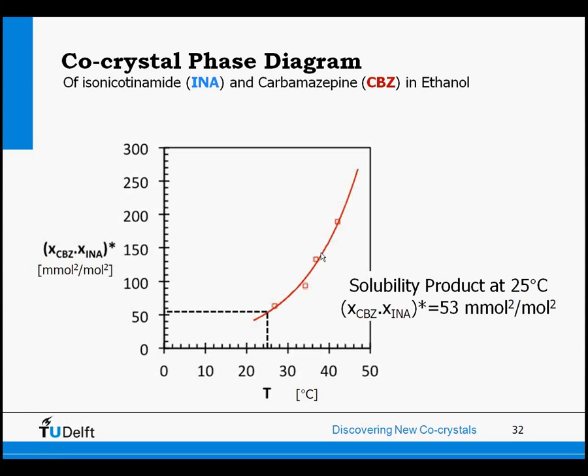And also here you can use the van 't Hoff equation to plot this. But here I use just the solubility product against temperature, and I indicate here a temperature of 25 degrees, and then you can establish that your solubility product of the co-crystal is 53. So that you can use to construct a phase diagram at 25 degrees.